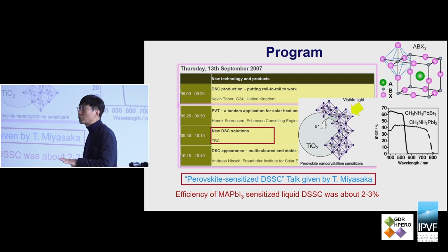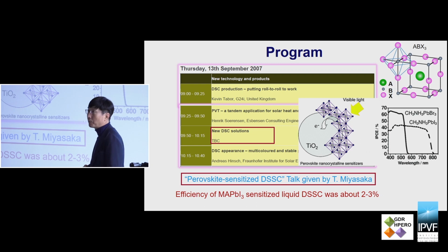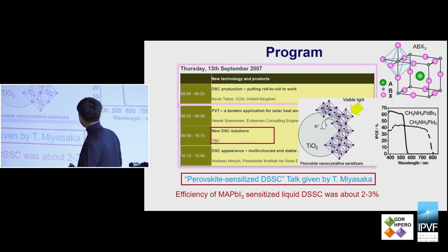This is not good for the conversion efficiency, but the shape of this IPCE spectrum is pretty much the ideal case, because from the low wavelengths to the high wavelengths it is an almost constant value. This is good news. So when I take a look at this IPCE spectrum, this will be a very good material if we further increase the absolute value of the IPCE spectrum.